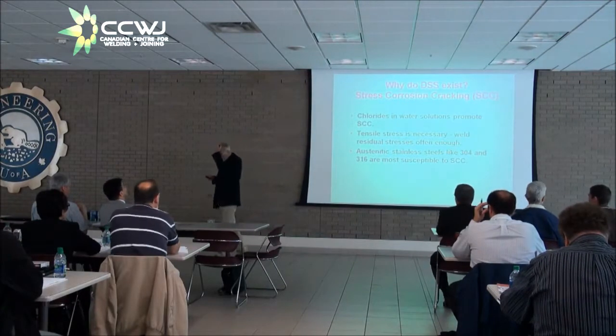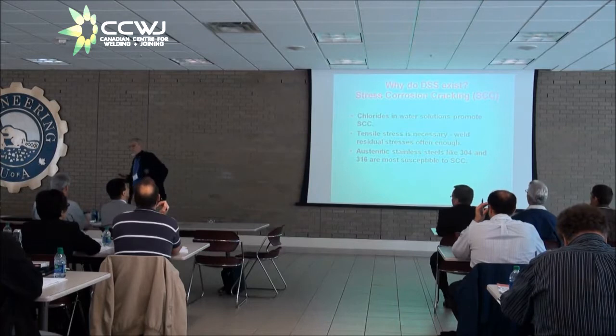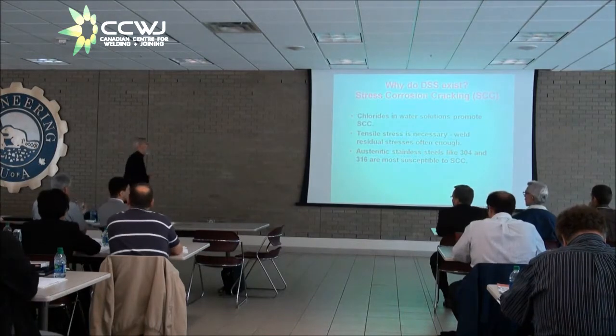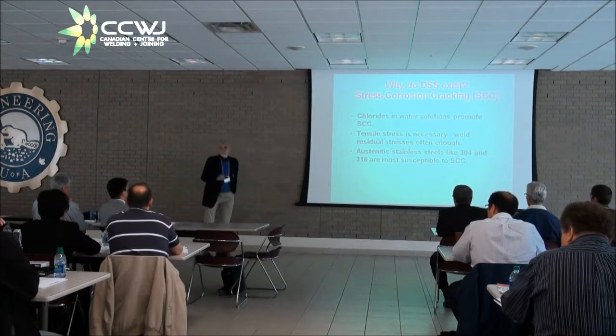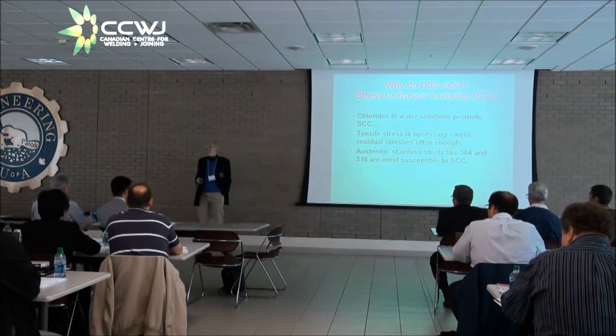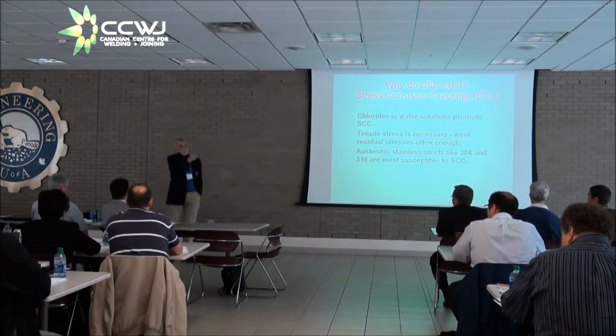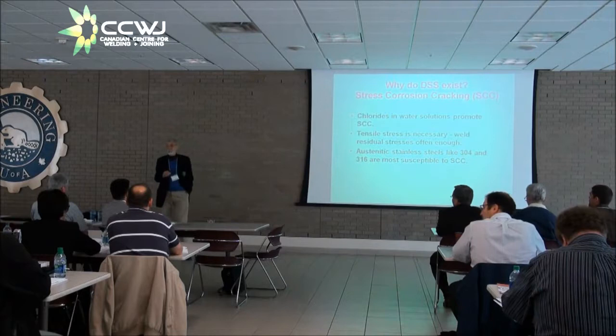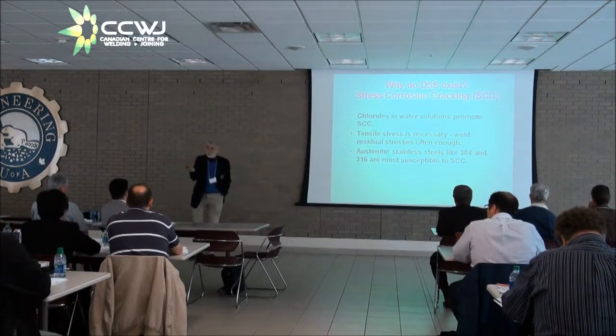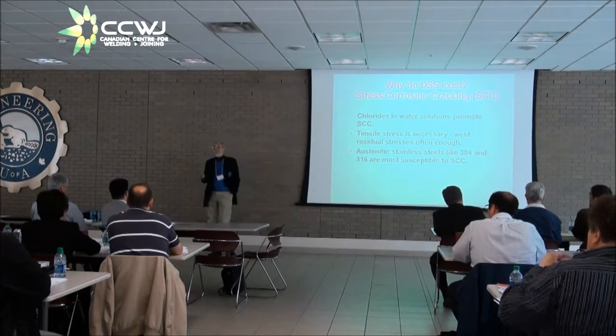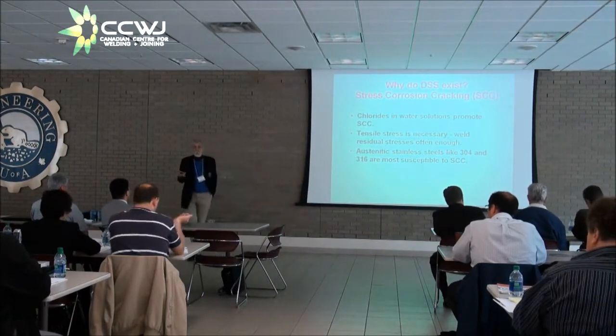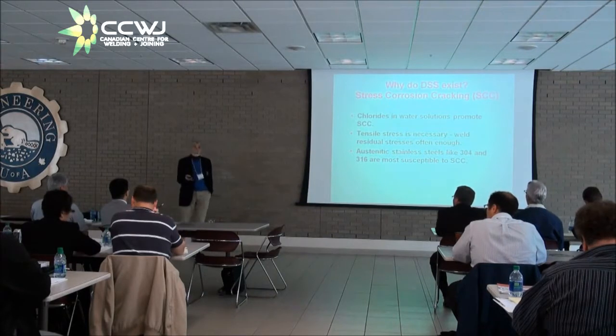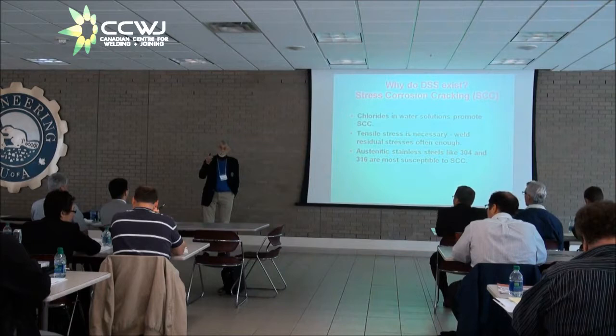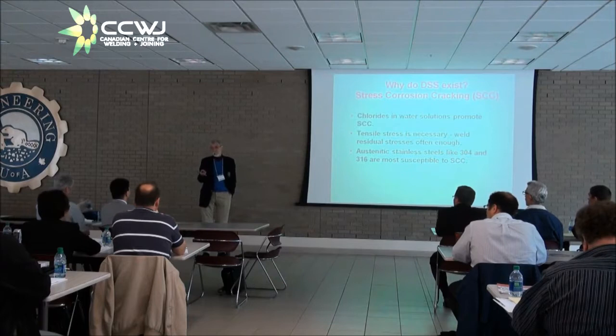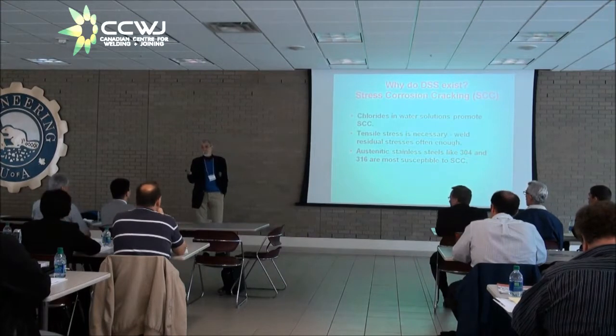Anyway, where I'd like to start is, why on earth do duplex stainless steels exist in the first place? Well, the answer is chloride stress corrosion cracking. We talked about all kinds of corrosion tests this morning, and it was always pitting. The real reason they exist isn't pitting. It's chloride stress corrosion cracking. The problem is that the austenitic stainless steels like 304L and 316L are highly susceptible to chloride stress corrosion cracking. The ferritic stainless steels are highly resistant to chloride stress corrosion. The ferritic stainless steels, however, are really ugly critters to weld. The reason is grain. The toughness vanishes when you weld on them because of grain.